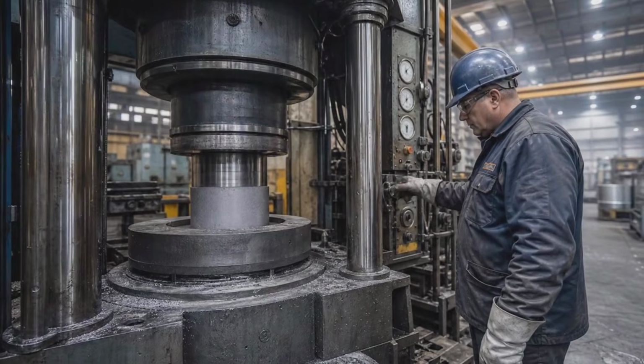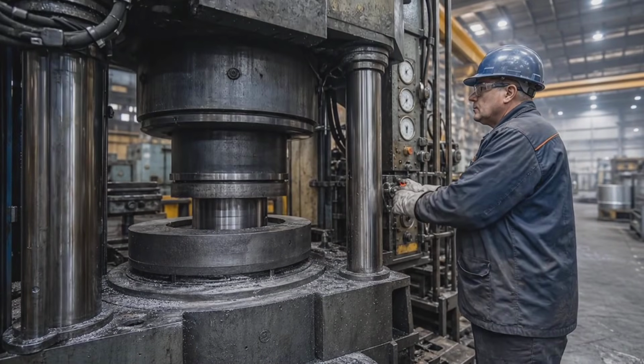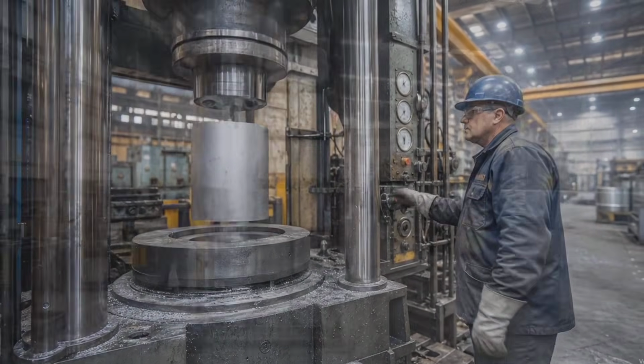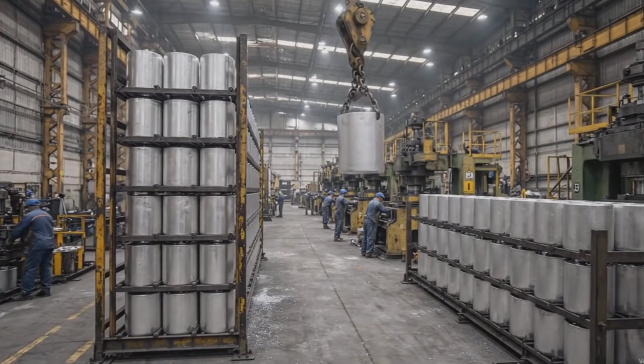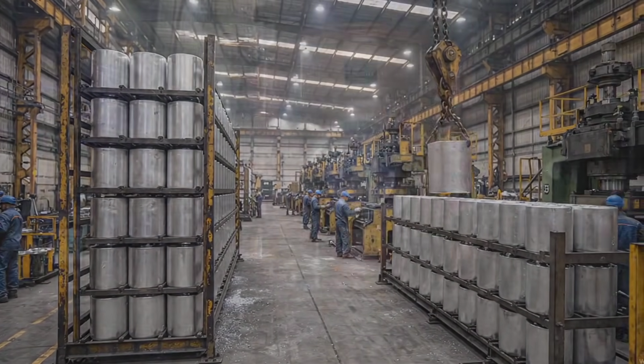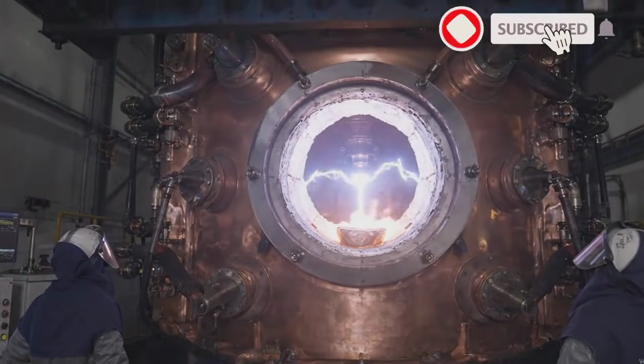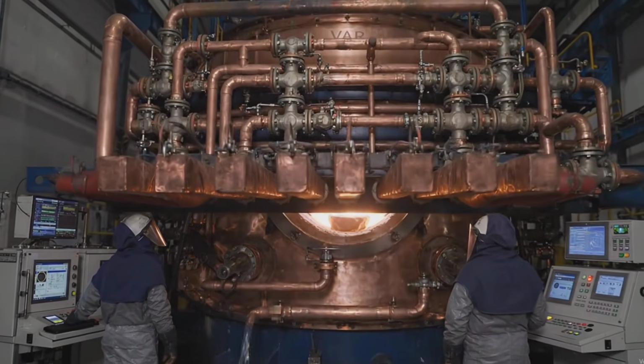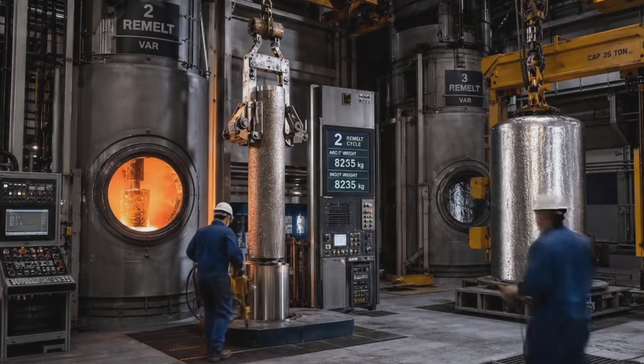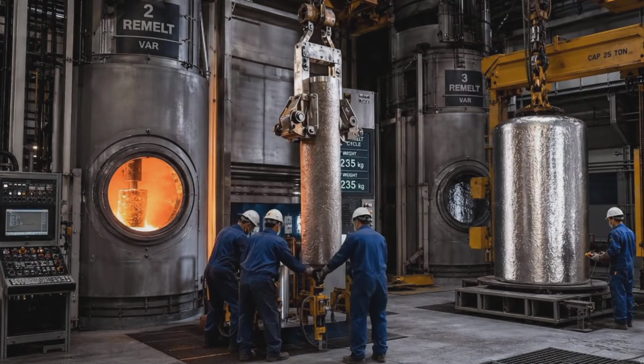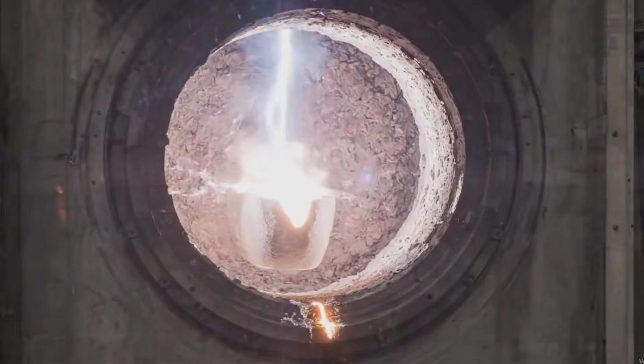In the alloy preparation room, crushed sponge is precisely weighed and blended with alloying elements, aluminum, vanadium, and others. The ratios are exact. There is no room for error. The alloyed mixture is compacted under massive hydraulic presses into dense cylindrical electrodes, solid metal rods ready for melting.